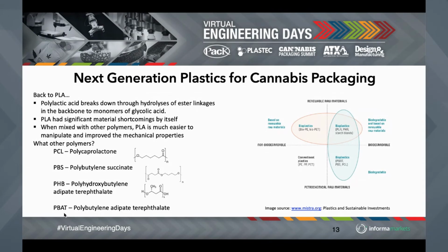So let's get back to the polylactic acid. Polylactic acid generally breaks down, again, through the hydrolysis of these ester linkages that I was talking about previously in the backbone of the monomers. And it breaks down to material called glycolic acid. PLA has significant shortcomings when you try and process it by itself. But when you mix it with other polymers, PLA becomes easier to manipulate, and it has much improved mechanical properties associated with it. What other polymers can you mix it with? PCL, polycaprolactone, PBS, polybutylene succinate, PHB, polyhydroxybutyrate, and PBAT, which is probably the one that most people use to mix with the PLA. It's called polybutylene adipate terephthalate.